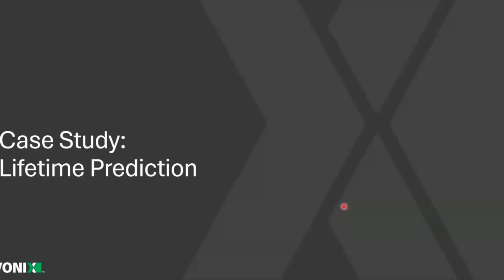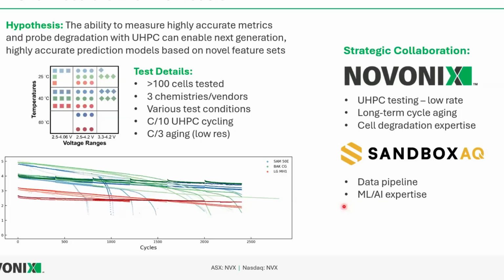So one last thing I'm going to cover is something that I've mentioned in the previous two webinars, just looking at lifetime prediction. Obviously, these advanced metrics with coulombic efficiency, slippage, capacity fade at these levels that were previously almost impossible to obtain, maybe we can layer these into machine learning models and create transferable models between slightly different chemistries to predict lifetime.